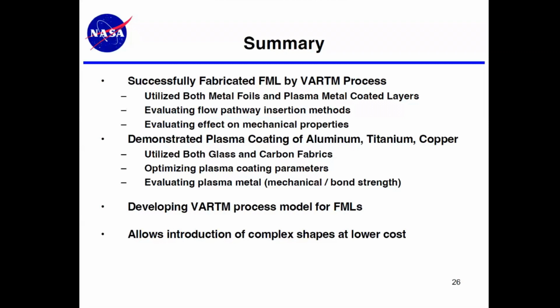And we did do some kind of crude testing of the plasma metal to fabric bond strength. We tried to measure the bond strength, and in essence, when we pulled the metal away, we just tore part of the fibers off of the fabric. So there appears to be a pretty strong bond between the metal and the fabric itself. So we have been developing VARTM process models for fiber metal laminates, and they are very similar to the standard VARTM process models, but they have been developed or are under development. And we have been able to introduce some complex shapes at relatively lower cost compared to presses and to autoclaves.